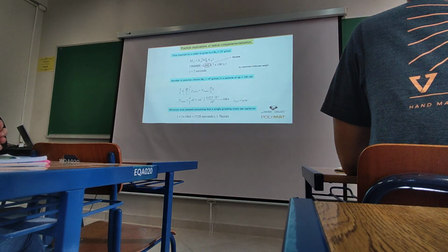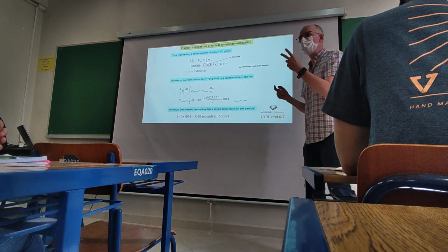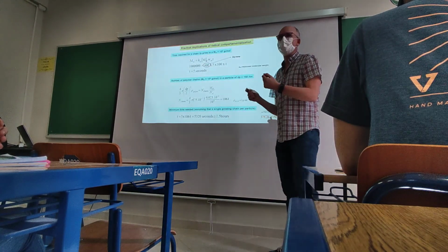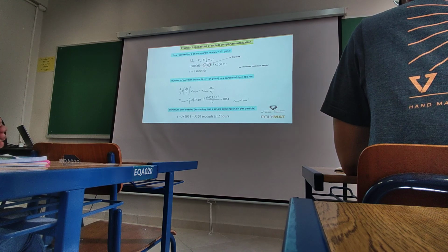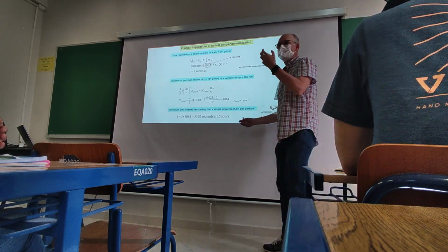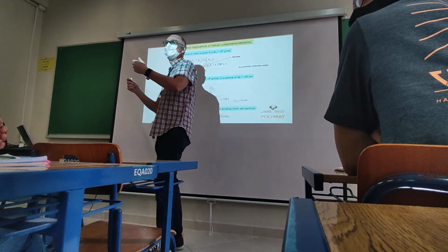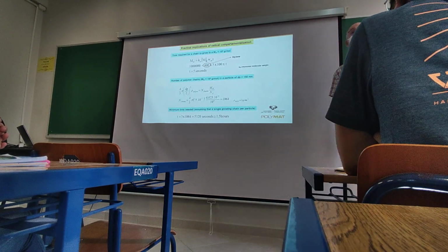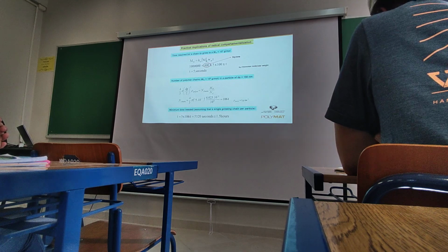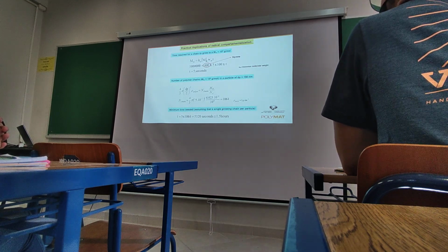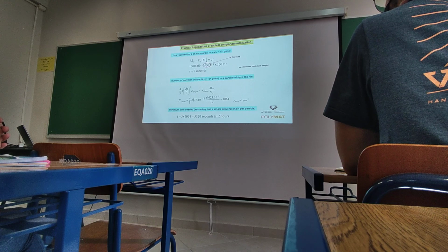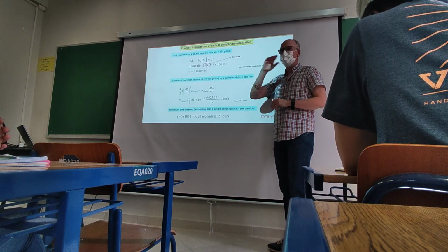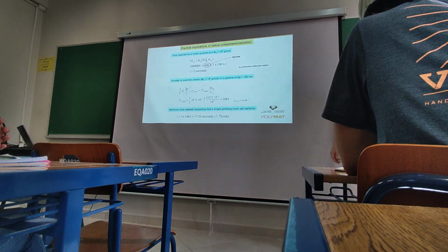Has someone of you run a polymerization of styrene in bulk or in solution, homogeneous? How much time do you need to create a solution of polystyrene in bulk or in homogeneous? More than 10 hours minimum. And probably you don't reach 100% conversion. In emulsion polymerization, in 1.5 hours, your reaction is finished.